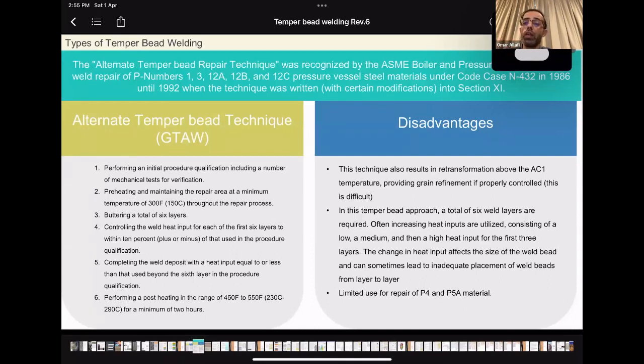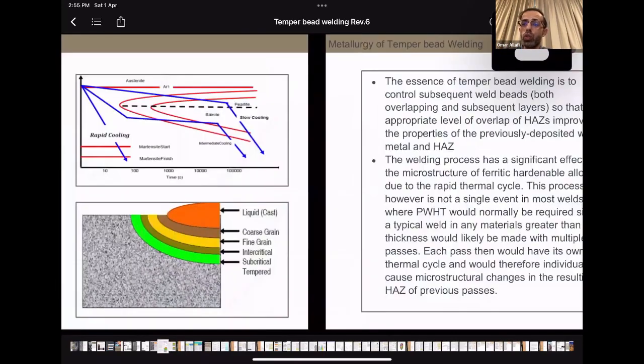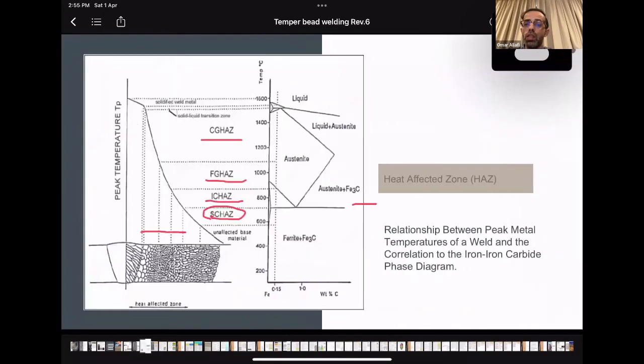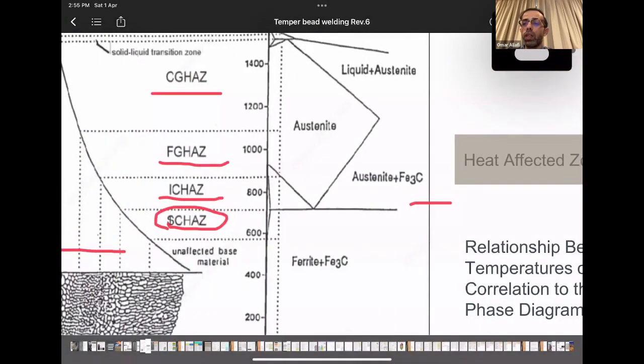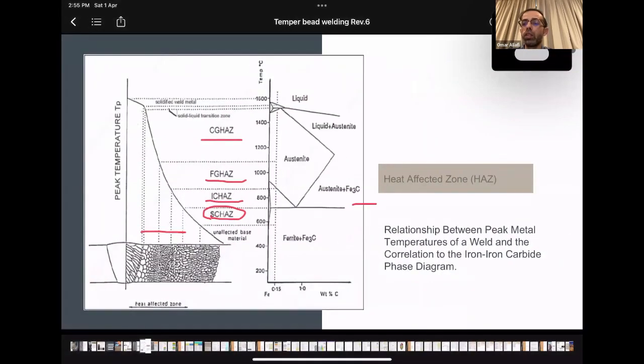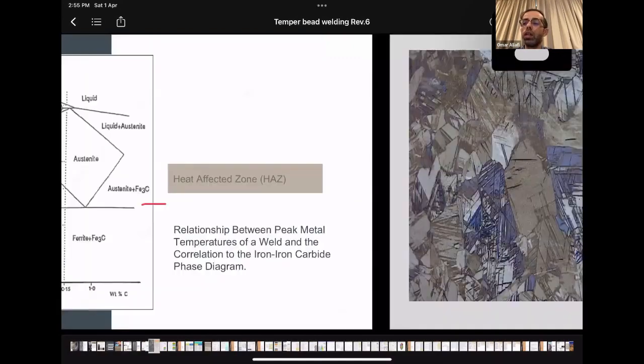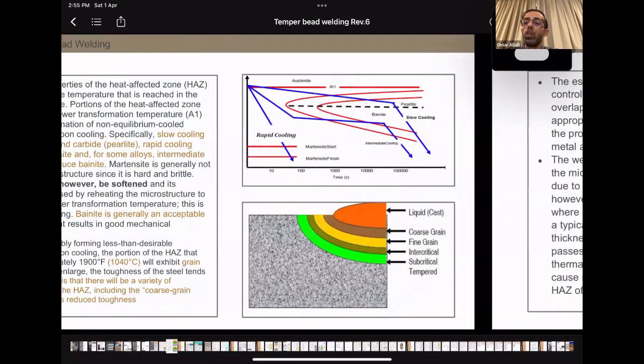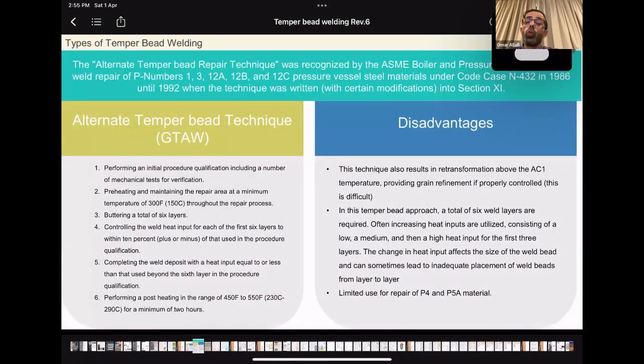This is AC1. I can go back to the chart just to show you. This is the temperature I'm talking about, the lower critical temperature. I'll be using this critical temperature in my presentation, and I'll refer to it as AC1 critical temperature. So this will take the base metal temperature above this lower critical temperature, and upon cooling, transformation to martensite and bainite will occur. This will enhance the toughness and reduce the hardness a little bit, but it's limited.